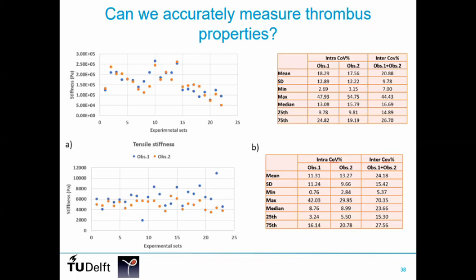So the take-home message here is, even under fully controlled circumstances, expect variations in the order of 10% with homogeneous samples, let alone what happens with heterogeneous samples. Well, don't stop doing experiments, but be aware of this, right?